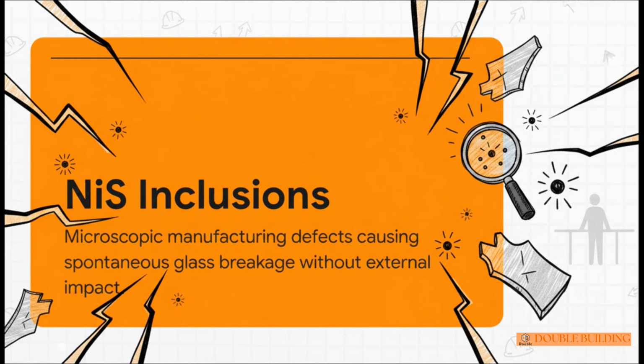Now, you might be wondering, why would a super strong glass panel break in the first place if nothing hits it? Well, enter nickel sulfide, or NiS inclusions. These are microscopic manufacturing defects hidden deep within the glass. Industry data estimates that roughly 1 in 3,000 to 4,000 panels actually contains this defect. And over time, these tiny inclusions expand, and they can cause spontaneous, catastrophic glass breakage without any external impact whatsoever. Zero warning. That kind of sudden monolithic failure is just an unacceptable risk when people's lives are on the line.